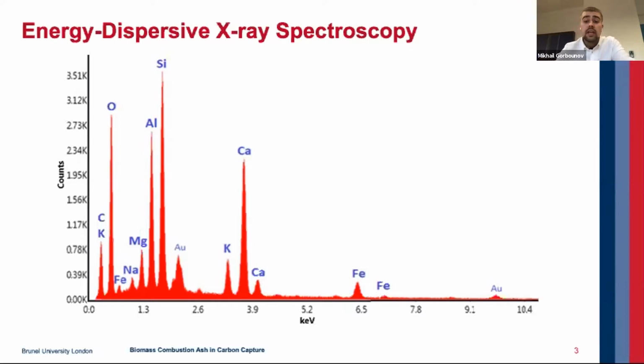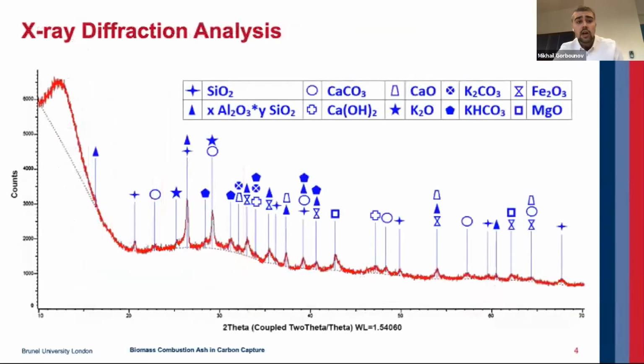Apart from this, we have also conducted an X-ray diffraction analysis, and the results are presented here. The investigated material is, as expected, a mixture of silicates and aluminosilicates with an abundance of inorganic mineral phases such as metal oxides and carbonates. Of particular interest is the potassium carbonate, K2CO3. It is believed to be a substantial contributor to chemisorption of CO2, as in the presence of moisture, the potassium carbonate, the same though could be said about lithium carbonate and sodium carbonate, would transform into potassium bicarbonate, also known as potassium hydrogen carbonate, and shown there in the blue hexagon on the slide.